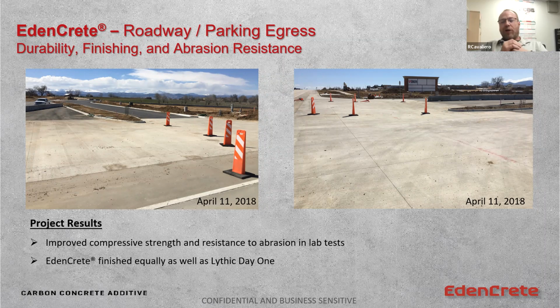Depending upon what your base concrete is that you're using, because we're putting EdenCrete into mixes. We're not coming and saying you have to use the EdenCrete mix. We don't say we need to do a 6-month-long study so you can use EdenCrete. You say, I have a mix that's in a spec, what am I going to do? We say you add a gallon of EdenCrete, or a half gallon. And we reduce the design water content for the volume of EdenCrete that goes in, so that your water to cement ratio stays in line with the design.